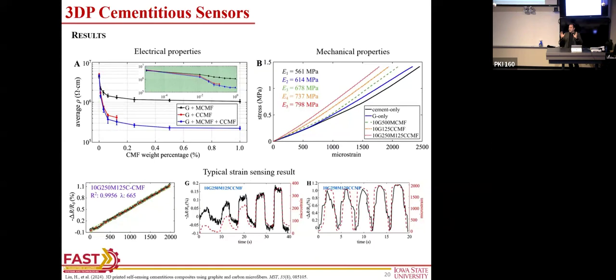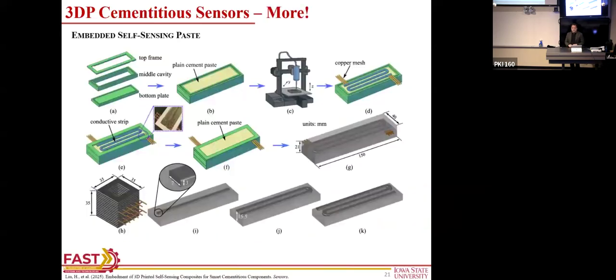Okay, so that's the story. We made toothpaste that works. We're good. But now we want to integrate it into the printing process, right? That's the main challenge. So the next step was to embed it in concrete. So concrete and a cementitious sensor. So we've taken the traditional method to do it, a cast. We cast half of the beam, we 3D print a layer, and then cast the other half. And that's our embedded sensor that we have.